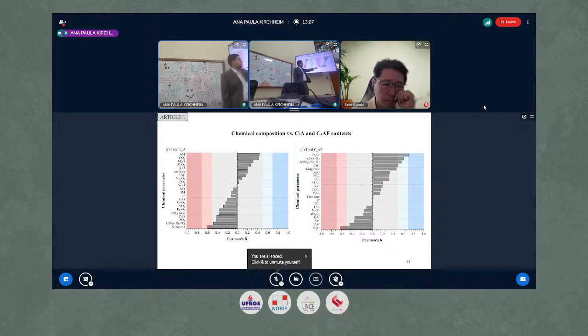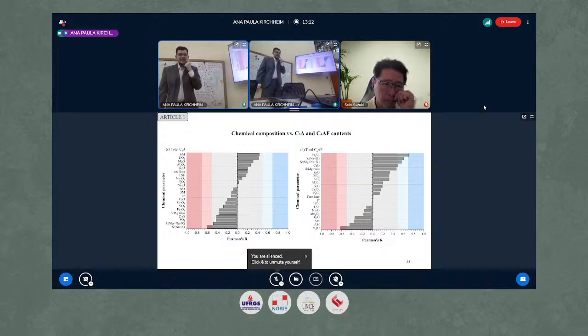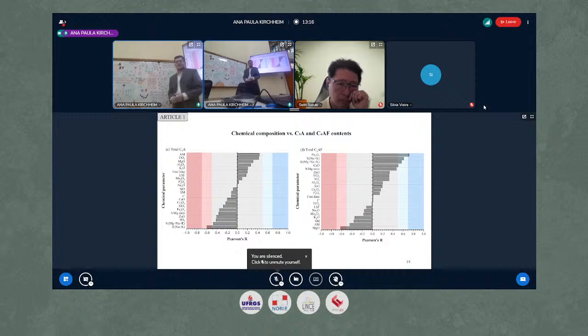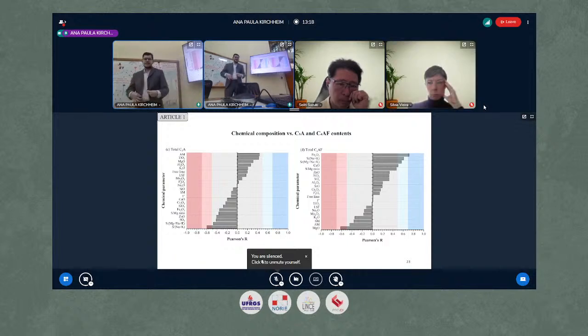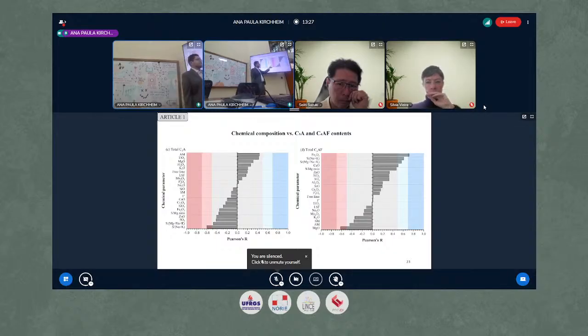Here it is also interesting to see magnesium appear again. It is very influential, and the higher the magnesium, the lower the C4AF. This is interesting. We saw some compatible results in the literature, but later some partners observed something somewhat different: magnesium stabilizing C4AF. So we need to progress on this type of study, the role of magnesium on the aluminates.